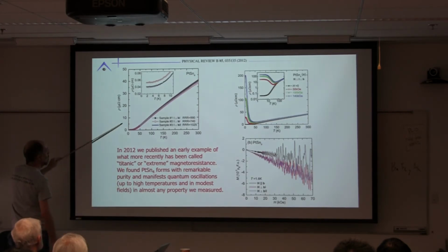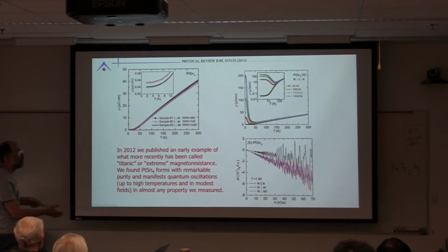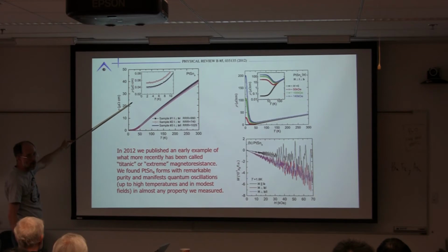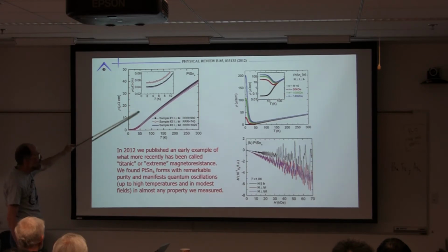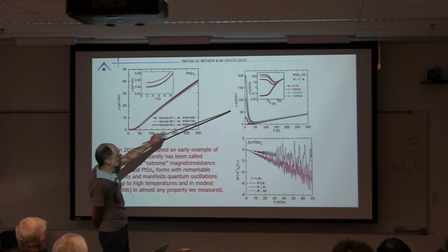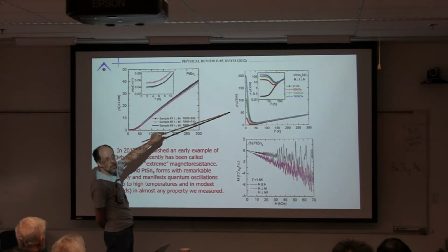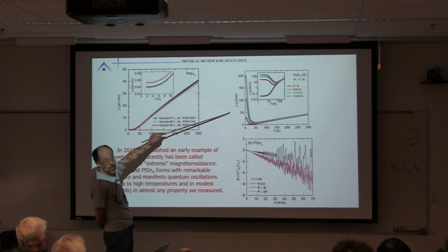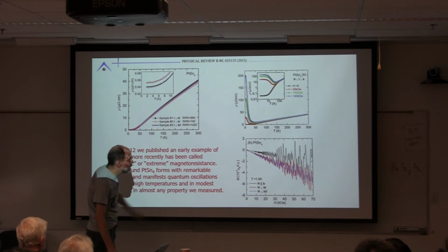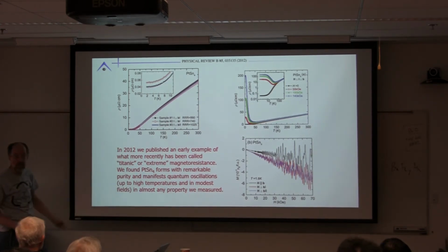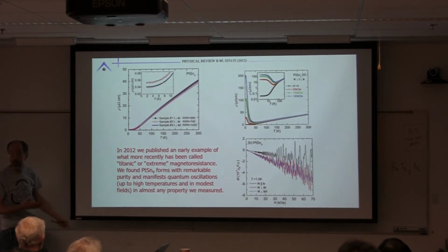Well, this material, when we looked at it in 2012, it was before titanic and extreme magnetoresistance. We found it has an incredible triple R. And it has a phenomenal magnetoresistance. We have 500,000% magnetoresistance at low temperatures. Any property we look at, magnetic field bounces like crazy. We have quantum oscillations in anything we look at.